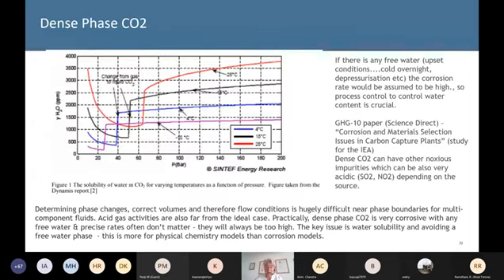I wanted to slip in something about dense phase CO2, because this is a really hot topic for people. And at high pressures, of course, we get a change of CO2. When we're talking almost 100% CO2 here, we get a transition of a liquid phase at high pressure and a swap over into the gas phase here, and that's what's going on at these transition points depending upon the temperature.